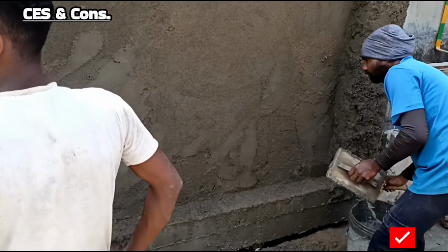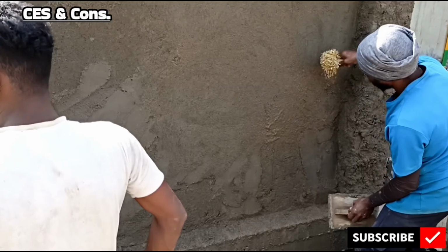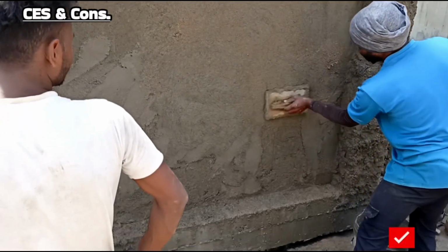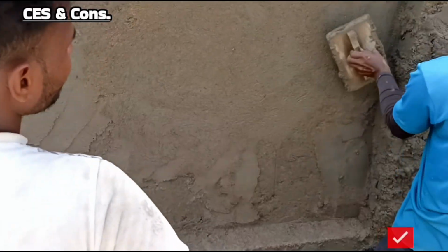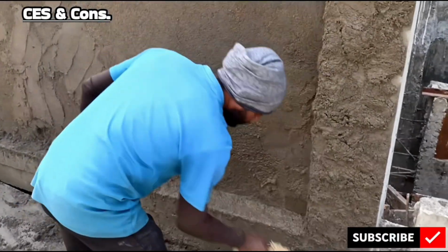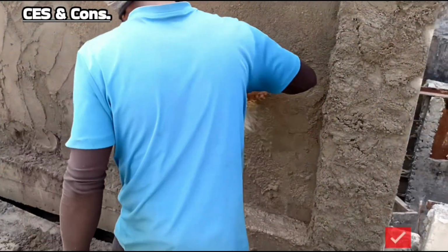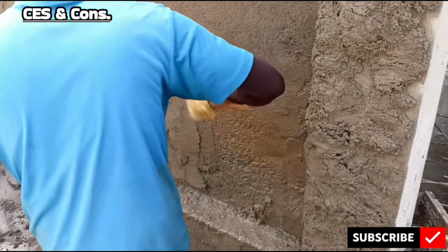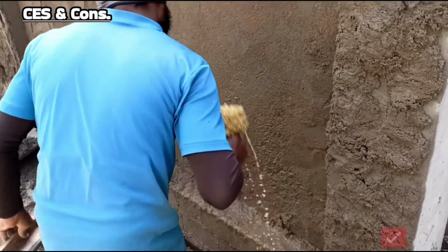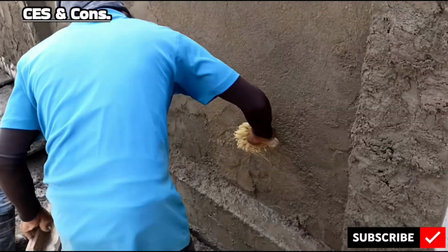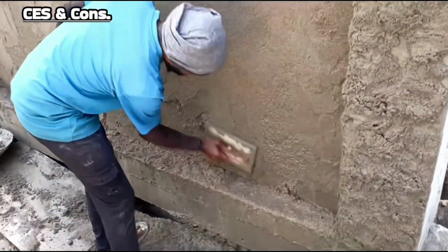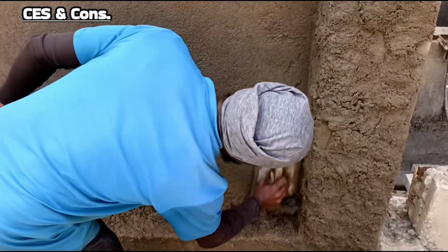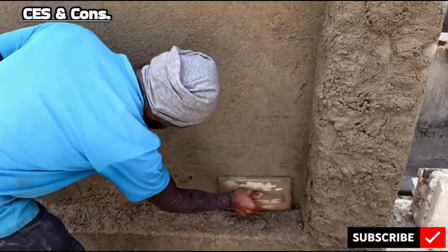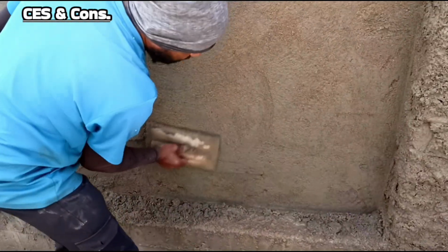According to IS 1661-1972, before plastering the masonry surface must be properly prepared. Cleaning. Remove all dust, loose mortar, efflorescences and oil stains. Raking of joints. Mortar joints should be raked to a depth of at least 10 to 15 mm for better bonding. Dampening. The wall should be well soaked with clean water 6 to 12 hours before plastering to avoid absorption of water from the mortar.